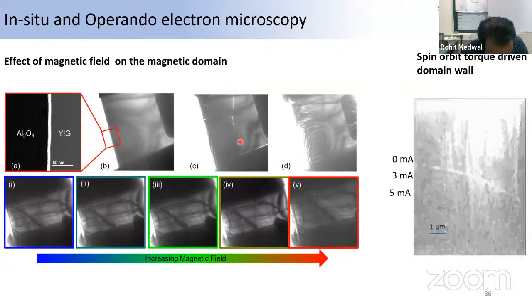And how to confirm this is a domain? Because we can switch the direction of this domain by changing the magnetic field. You can see that this white becomes a dark line here, keeping the same parameters constant. And this shows that we are able to switch the domain directions by changing the magnetic field. And you can see that this domain is here. Maybe I'll just use the marker to highlight that this is my domain wall. And we can use the applied magnetic field to propagate this domain wall from one state to another state, which comes to here. So we confirm that we can propagate this domain wall from one state to another state.